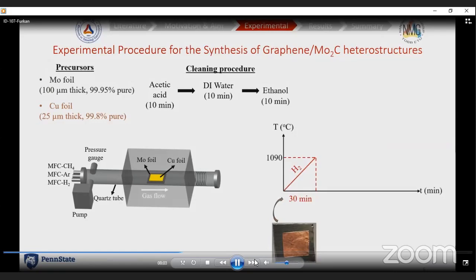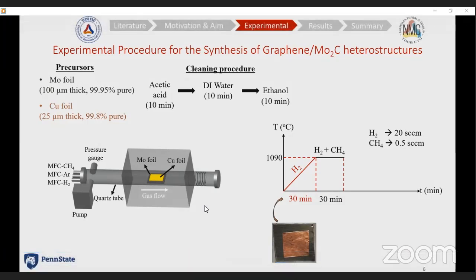And since this is higher than the melting temperature of copper, after the copper melts, CH4, the methane gas, was introduced into the CVD chamber with a flow rate of 0.5 SCCM. And at this temperature, for 30 minutes, the molybdenum carbide crystals were grown. And finally, the system was cooled down to room temperature in 2 hours under hydrogen atmosphere.